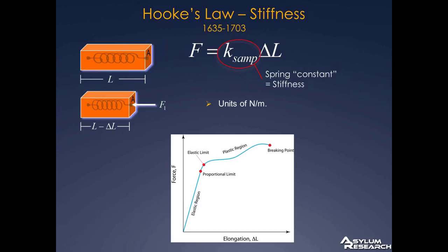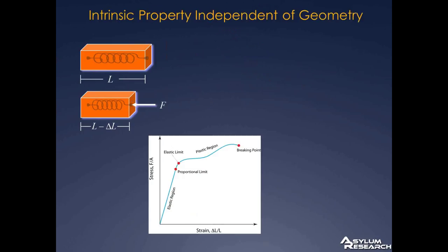Finally, I should note that many materials have a time-dependent stiffness or time-dependent modulus. That is, they relax. For nanomechanical measurements, it means that the stiffness and the modulus depend on how rapidly the measurement is made. Put another way, there's a frequency dependence to the measurement. So far, we've focused on measurements of stiffness, which has units of newtons per meter, the spring constant of the material.